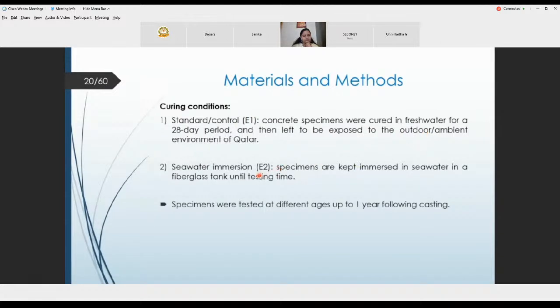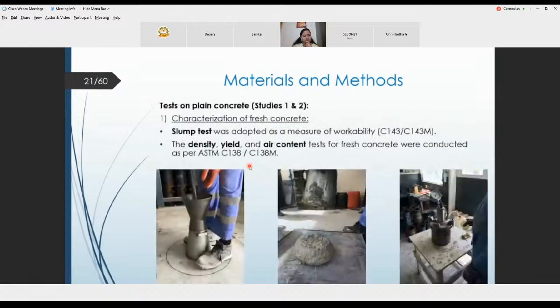The second condition, E2, is the seawater immersion, where we actually exposed the specimens to the harsh environment of seawater, immersing the specimens in seawater in a fiberglass tank until testing time. The specimens were tested at different ages up to 1 year following casting.